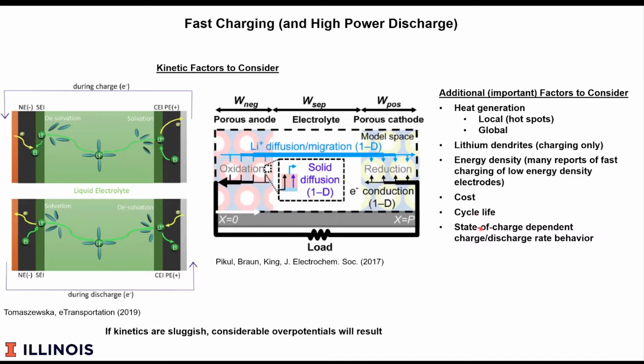Another complicating factor is that there's a state of charge dependent behavior. And that's because the electrical and ionic conductivity, as well as the association constants, vary with lithiation and delithiation. So while you may be able to fast charge at 50% charge, you may not be able to fast charge at, say, 10% or 90% charge. And it's important to take that all into account.